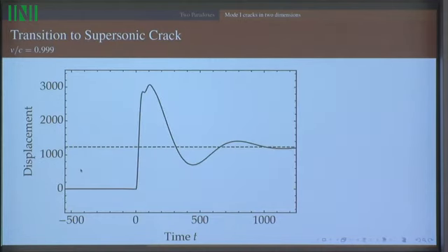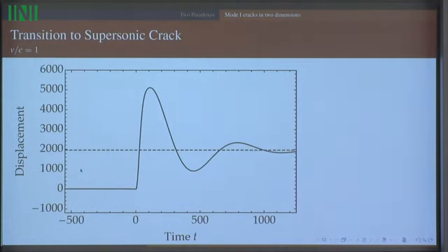99.5%, 99.9%, almost nothing like the square root anymore. And now, precisely at the Rayleigh wave speed, the solution has changed character. It's going too fast now to excite any of the waves. It's just gone supersonic, so it's really leaving a sonic boom in its wake.